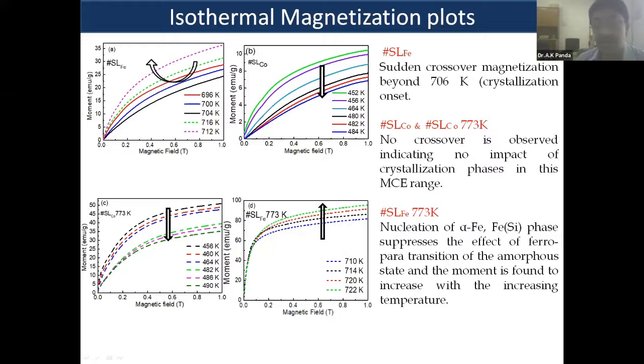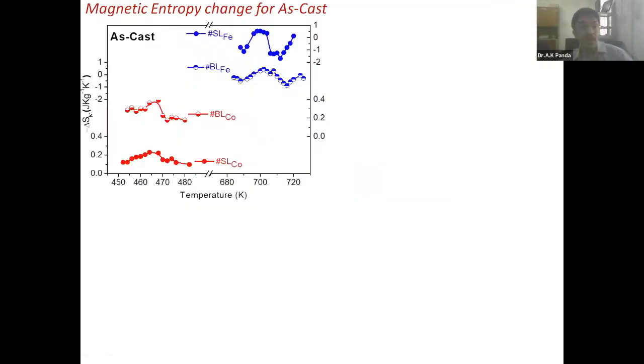As you raise the temperature, there is a crystallization, and therefore, with a change in moment, you find a change in the crystallization. So what you find in the case of iron is that it first decreases and then increases, and in the case of cobalt, it goes on decreasing. So it is basically the type of second phase that is generated that is modifying your moments, right? So I move further. I think this may be interesting to you because this is a plot of your entropy with respect to your temperature, and you find the single layer iron and bilayered iron phase.